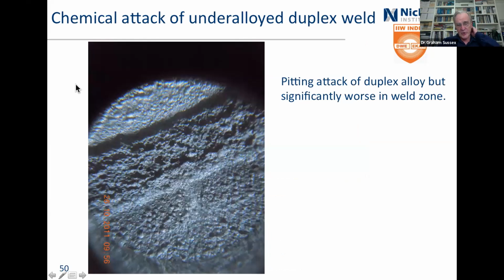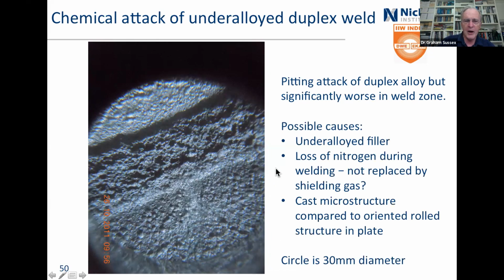This is a piece of duplex which was in a fairly aggressive environment. The distance across there is about 30 millimeters, but as you can see, the weld has actually been attacked much more severely than the gross metal out here. My understanding from looking at the data was that they basically under-alloyed the filler. They had the wrong filler in there. It's possible that they lost nitrogen, that they didn't have any nitrogen coming in, but I was not able to verify that. Certainly the filler looked to be wrong. The other thing is that here we've got a nice oriented microstructure. Here we've got a spiky sort of microstructure, which is actually going to be more susceptible to corrosion.